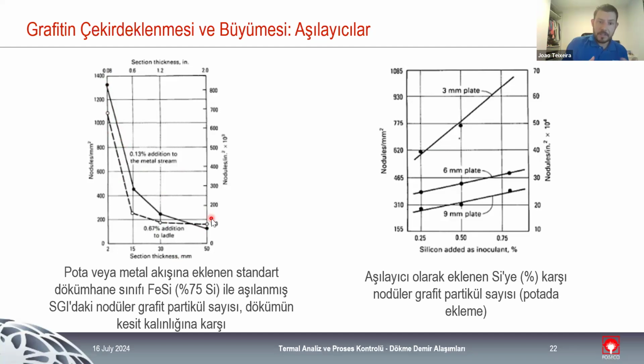And for these particular cases, we have to be really careful with inoculation, because we need to give a lot of stable nuclei to the melt to start solidify, because the solidification takes so long that after some time, some of the inoculants that you are going to add could disappear, and we don't have the effects of them in the melt. So we need to be really careful with them. And you can see that there is an effect of the type of inoculation that we have on the nodule count that we get in the cast.